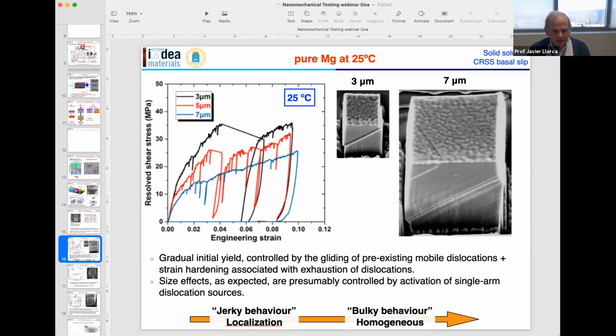One of the things that you can see is that you have a gradual yield of the material in all cases. This is controlled by the gliding of pre-existing mobile dislocations. But because the micropillars are small, particularly in the 7 μm, there is a point in which basically you have a lot of hardening because you do not have enough dislocations to accommodate all the plastic deformation. You are increasing the stresses, and then you have a localization of the deformation. So you activate one of these sources, and then you have the formation of a slip band.